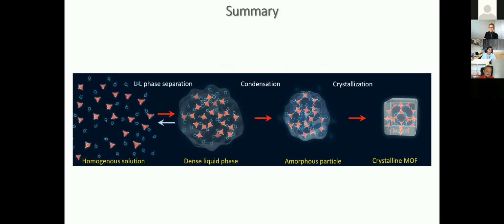So just to summarize this part of the talk, and this is not just for MOF, as I showed you, this also applies to metals, right? You start from a solute-rich phase, you condense into this dense liquid or solute-dense phase, and then this phase can go back and forth, and then you form an amorphous phase, right? So here is what we saw. Whenever you form this dense phase, and the dense phase collapses into the amorphous phase in our in situ movies, we never saw it going back. But at this point, this is the decision-making step. Here you can still disappear. But once you form this amorphous aggregate, most likely you end up going to the next stage, which is crystallization, or formation of the MOF crystal.